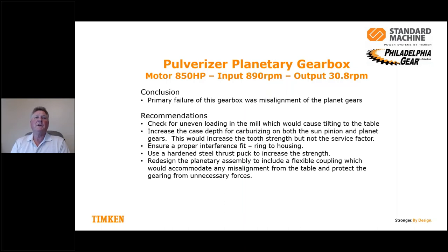But the primary recommendation for this gearbox was to redesign this planetary assembly to incorporate a flexible coupling. This would accommodate any misalignments from the table to protect the gearing from unnecessary forces. So really, the part of the gearbox that we could improve was putting a flexible coupling in, and it would allow the planetaries to run in a proper condition without all the forces that are coming from the mill above it. That was number one. A redesign was really necessary for this gearbox.